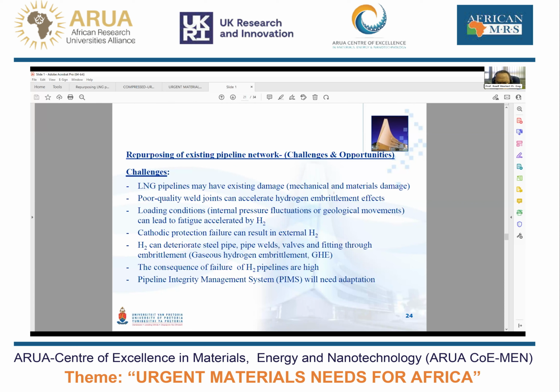Cathodic protection is commonly used for these pipelines, and the failure or poor operation of these cathodic protection systems can result in hydrogen being generated on the external surfaces. The internal hydrogen can deteriorate the material through a specific degradation mechanism referred to as gaseous hydrogen embrittlement, or GHE. Because the consequence of the failure of a pipeline carrying hydrogen at high pressure is very high, the pipeline integrity management systems of these pipelines will then need stringent adaptation.